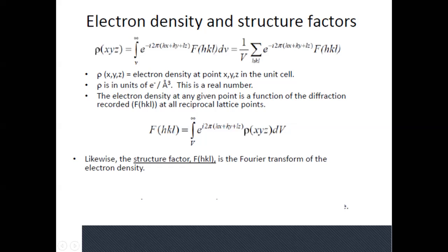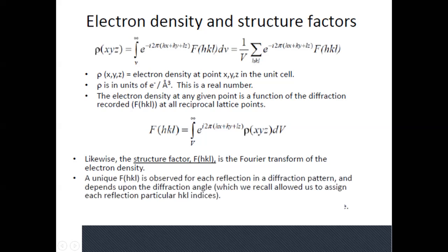And so this is a very important component here, the structure factor. We'll be looking at that quite a bit. This is the key thing to solving and refining a crystal structure: how well the observed structure factor matches the calculated structure factor. And so there's a structure factor observed for every reflection in the diffraction pattern. And again, it depends on the diffraction angles to determine what particular HKL indices it is.